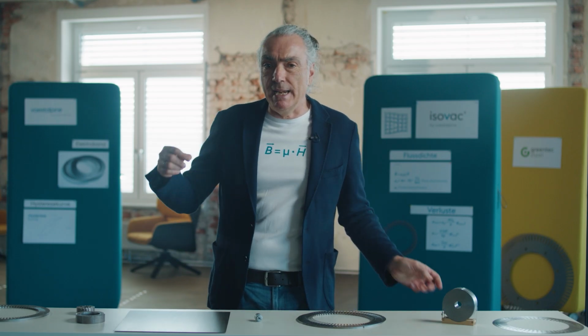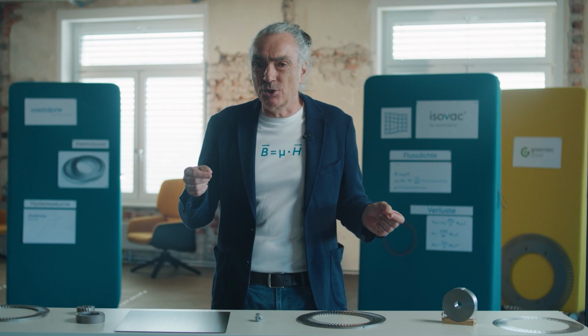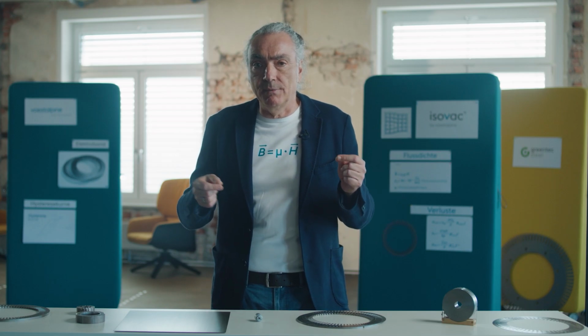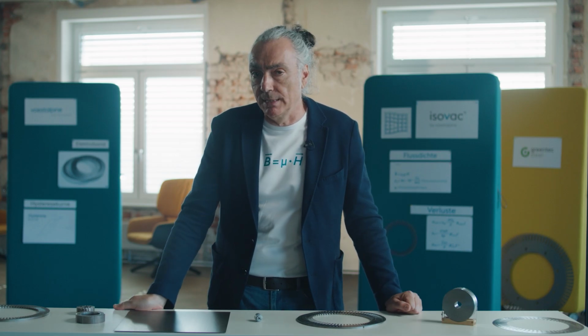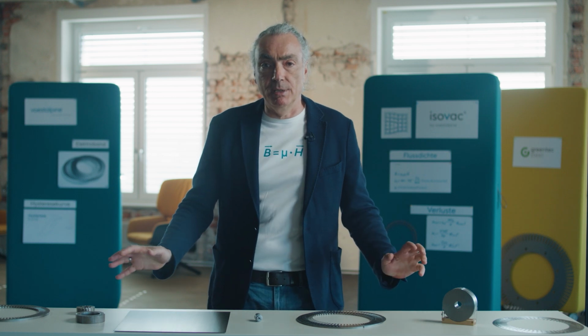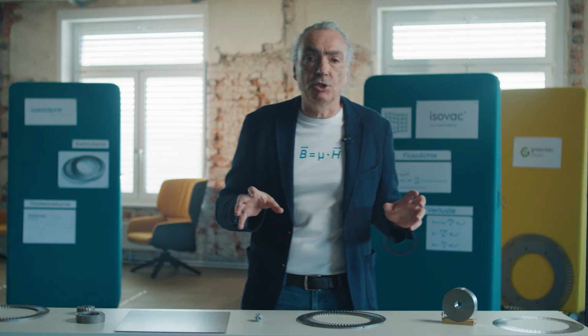So the thickness of the material is of crucial importance, especially in the case of very fast rotating motors. Special alloys such as silicon, aluminum or manganese make a further contribution to the reduction of eddy current losses. These reduce the conductivity of the material, meaning that the current doesn't flow as easily and the eddy currents cannot become very big. Let's summarize.